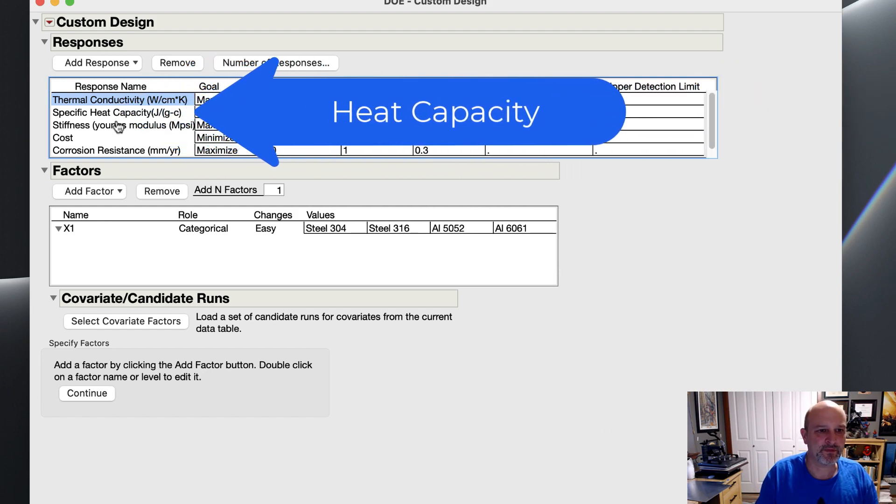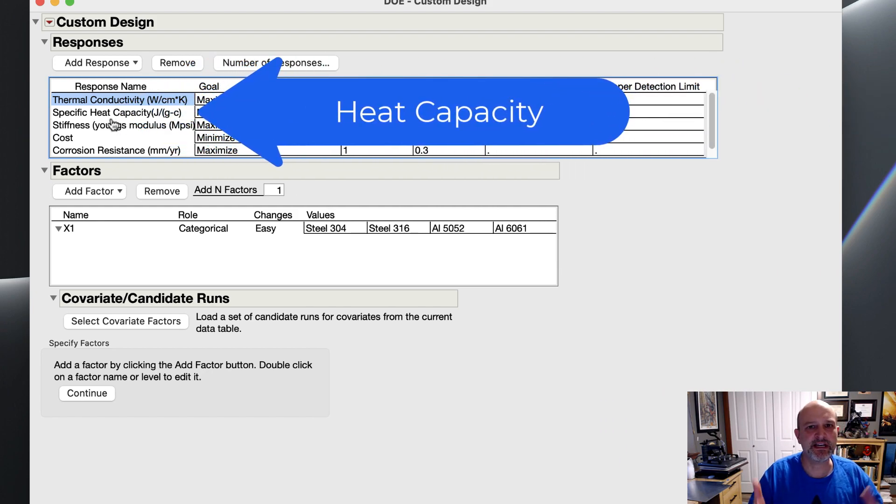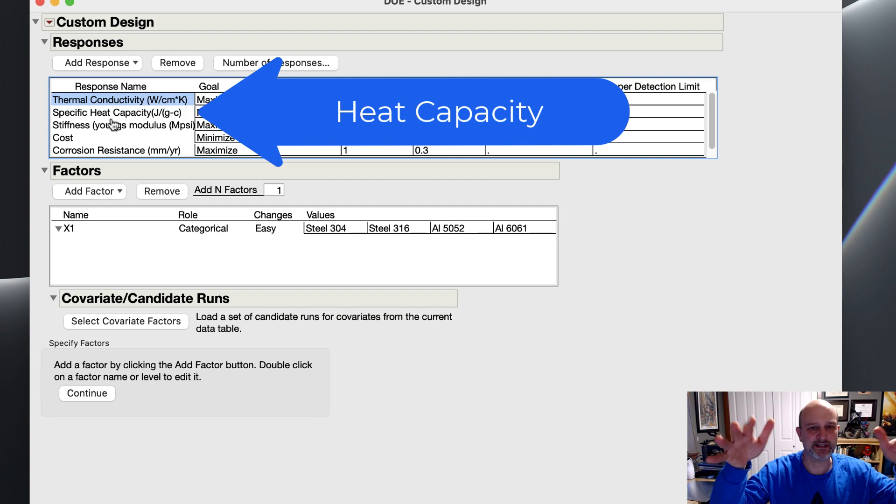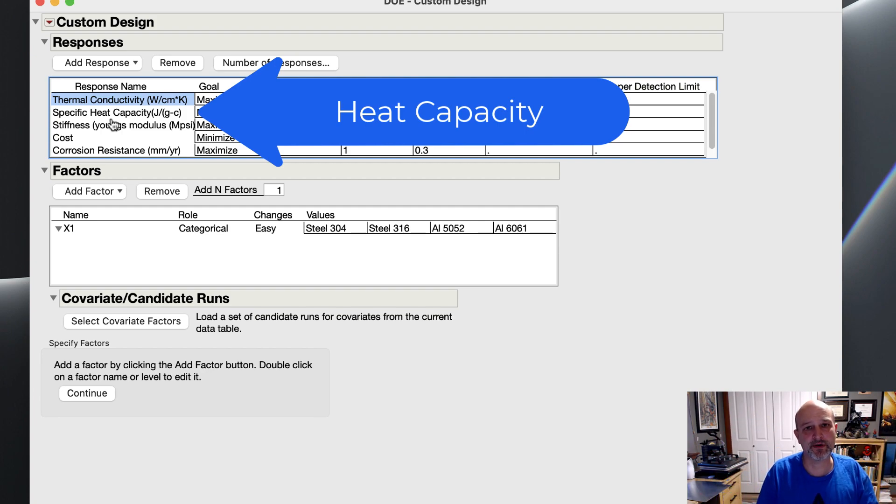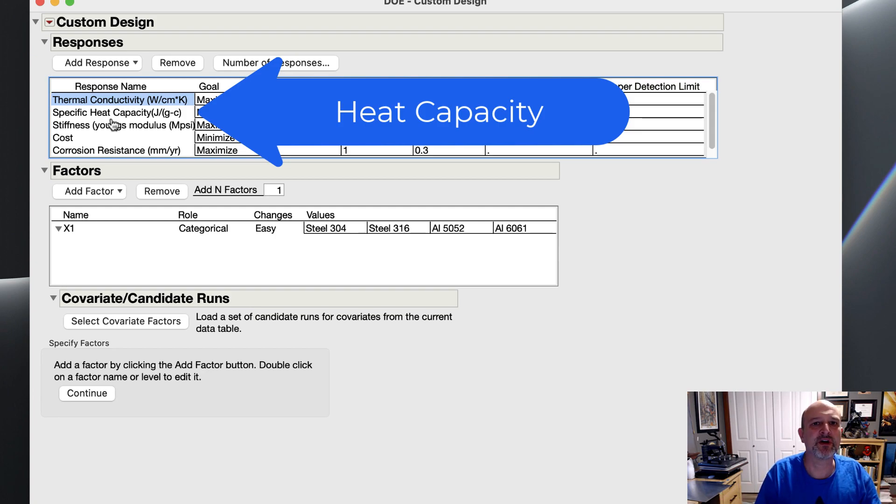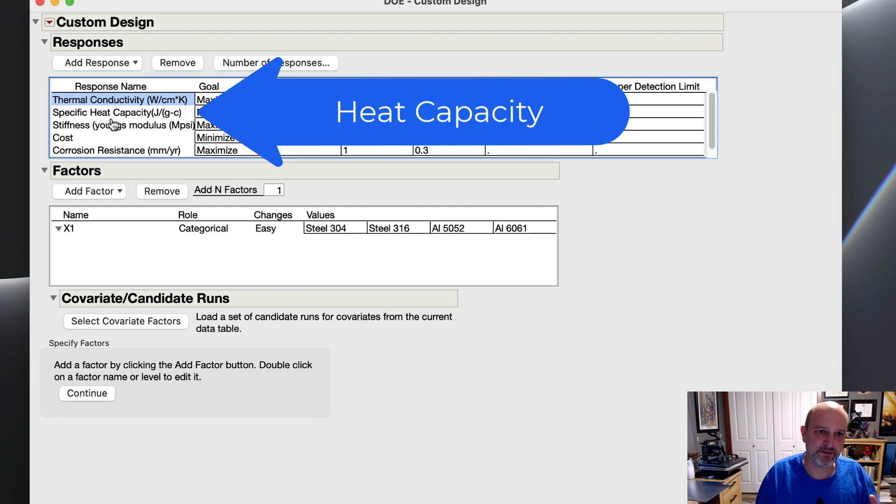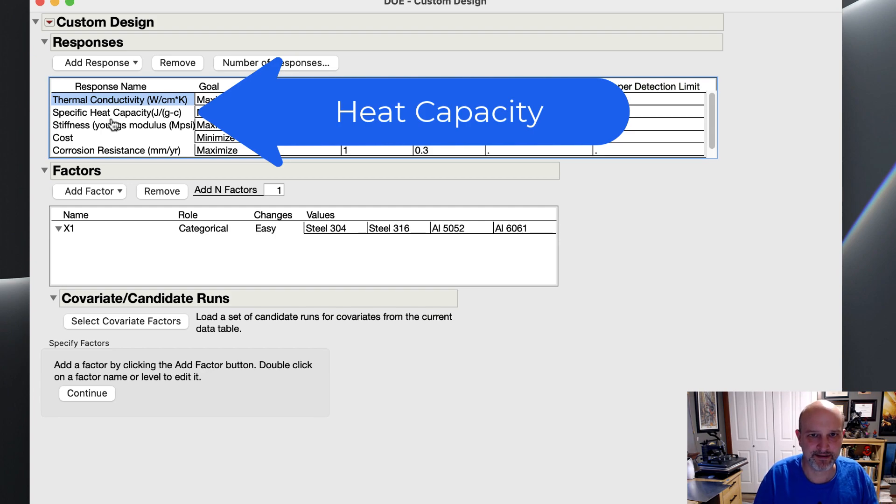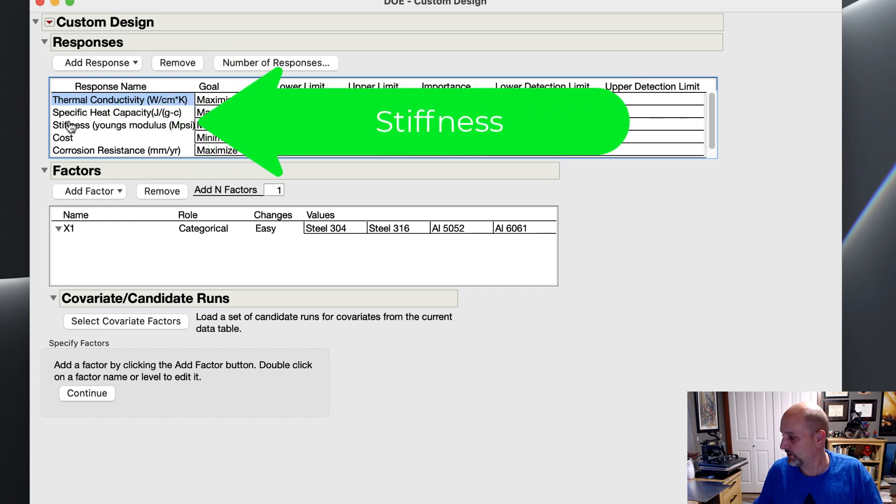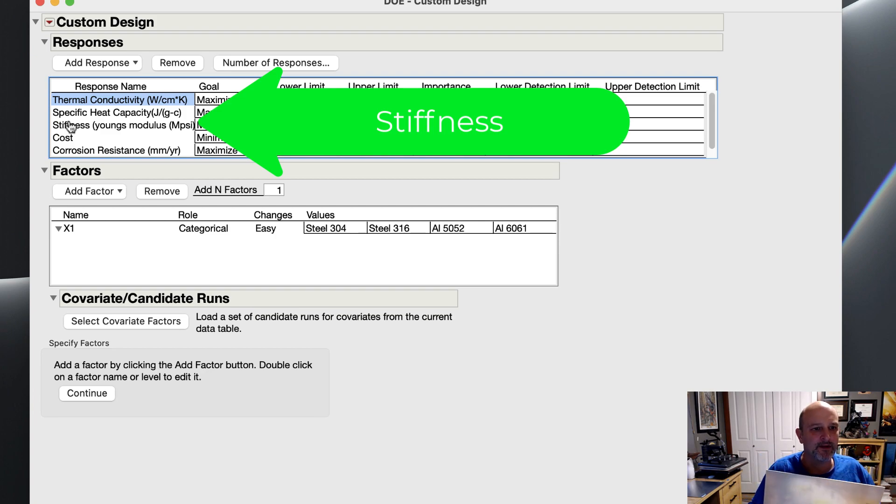Specific heat capacity, we want that also to be high. That's how much heat it can store up so that if you turn the heater off, it has that much held in it and slowly leaks it out to the book. Why do we want that? Because if we're going to heat the book, we're going to preheat underneath. We want a lot of heat stored there, a lot of energy stored there to come through the book. We want it to come through slowly because it helps to train the paper to be flat better if it cools down at a slower rate. Usually about an hour and a half, hour and 40 minutes is the ideal time to come back down to ambient. Stiffness, we want that to be high because we don't want it to bend or flex under normal conditions.